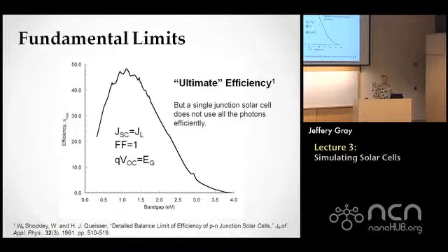And there happens to be a peak efficiency for that. And you can see for this particular spectrum, and I believe again this is the AM 1.5 direct spectrum, it peaks almost exactly where silicon is. So it's somewhat fortunate that silicon is so abundant and so popular a material, but also for a single junction gives us the most energy potential.